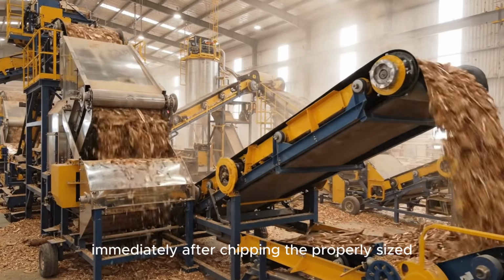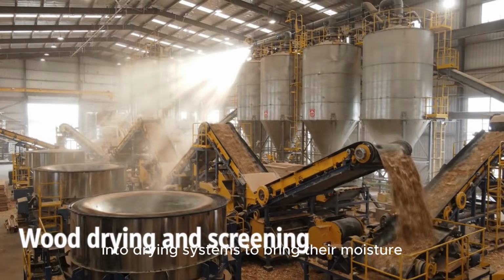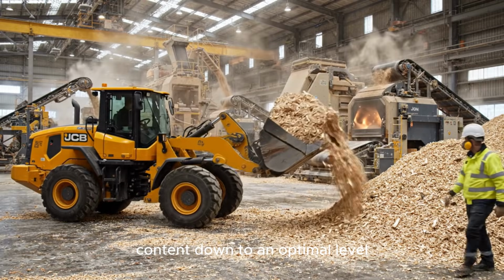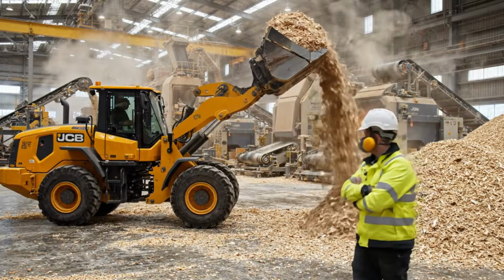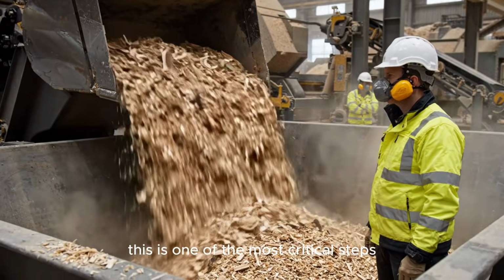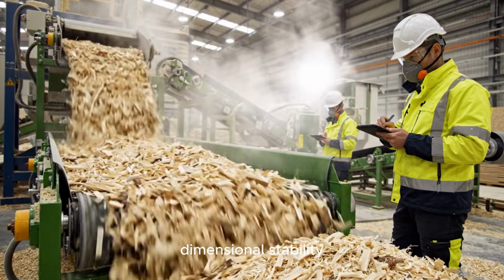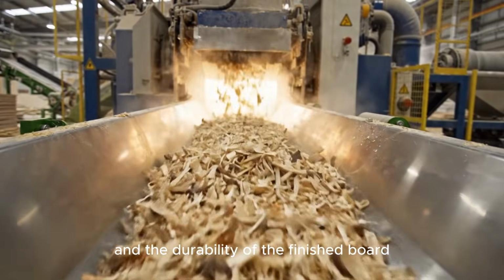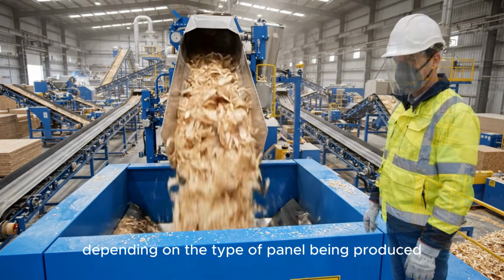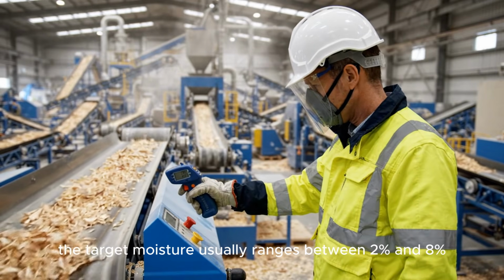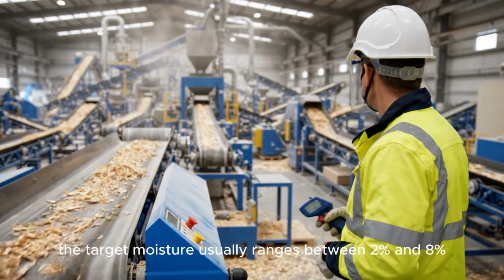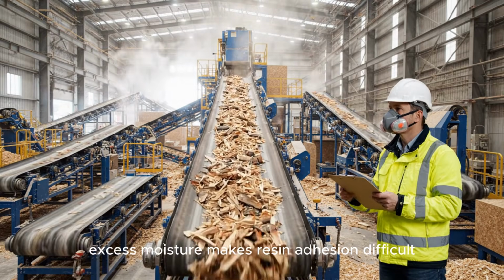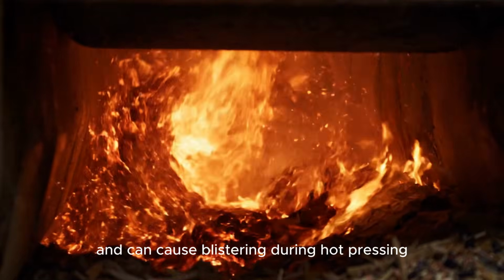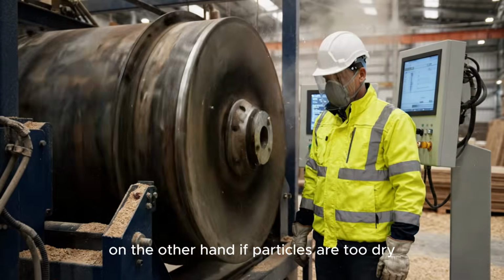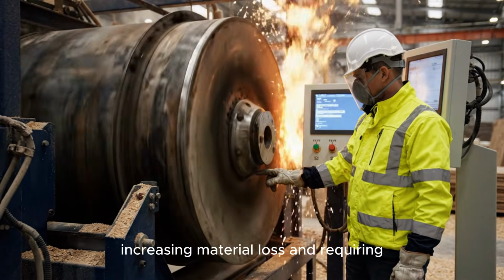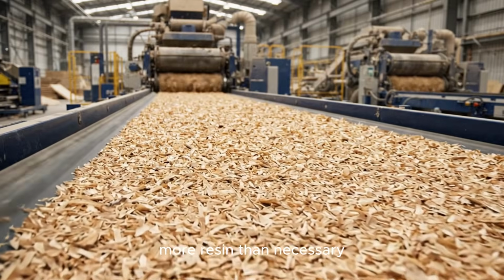Immediately after chipping, the properly sized wood particles are transferred into drying systems to bring their moisture content down to an optimal level before resin is applied. This is one of the most critical steps, directly affecting bonding quality, dimensional stability, and the durability of the finished board. Depending on the type of panel being produced, the target moisture usually ranges between 2% and 8%. Excess moisture makes resin adhesion difficult, weakens bonding, and can cause blistering during hot pressing. On the other hand, if particles are too dry, they become brittle, increasing material loss and requiring more resin than necessary.